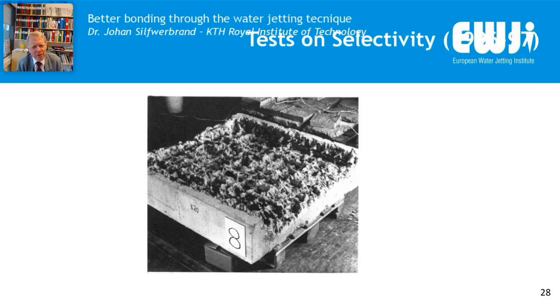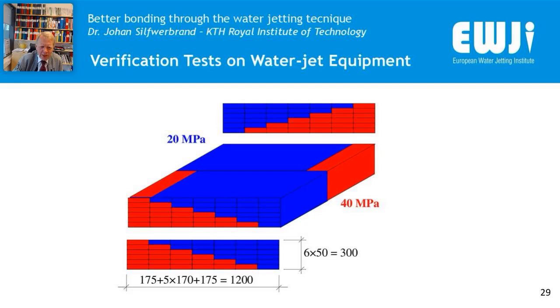One question here was about selectivity. And in fact, we have tested selectivity in the lab. We cast some slabs, and we made them of two types of concrete. And then we looked at the result. The ambition was to remove all low-quality concrete and keep all good quality concrete. And so here you can see that there were two stairs. The red color shows the high strength, or rather a medium strength concrete, 40 megapascal in compressive strength, and the blue is 20 megapascal, which is a low strength concrete.